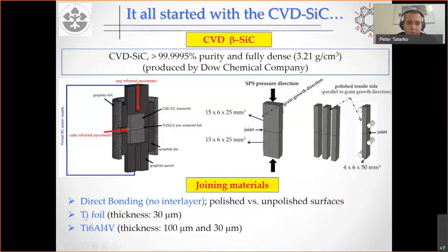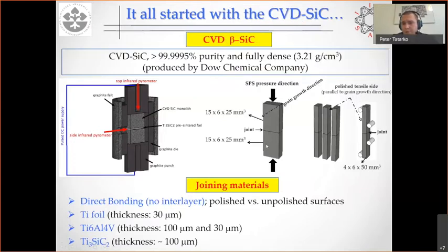In the other two cases, we used titanium-based foils, pure titanium and titanium, aluminum, vanadium foils. So we inserted this foil in between these two parts of silicon carbide, and we used it as an interlayer. In the last case, we also used the MAX phase, but it all has some reason which I want to now explain to you and convince you that it was a good option to go to. I forgot to mention, after joining, we cut the samples and then we performed some mechanical testing, as you can see here.